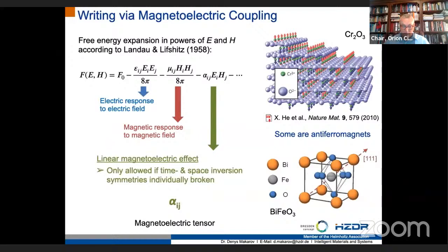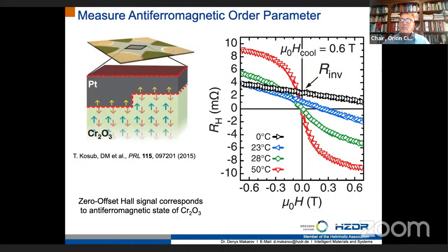Already from the 60s, it is known that this magnetoelectric effect is a linear magnetoelectric effect. It means that one can modify the magnetic state or the antiferromagnetic state of the material by the combined action of electric and magnetic fields. The very strong advantage of uniaxial antiferromagnet with an out-of-plane easy axis is the possibility to read out the magnetic state of the antiferromagnet unambiguously using conventional magnetotransport techniques.